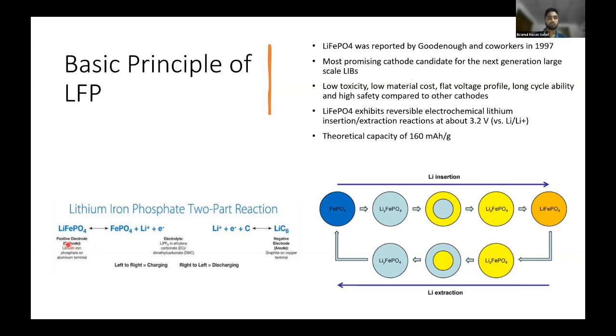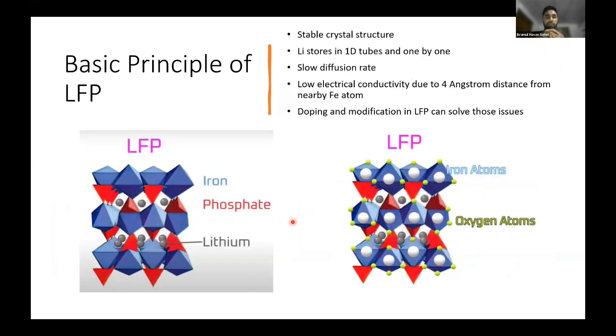So as you can see here in the reaction, when the lithium iron phosphate is fully lithiated, you get the lithium from it during the charging. And this lithium is alloyed on the anode side with the carbon. As you can see, LiC6, that means 6 carbon atoms hold one lithium inside. And that's how it goes back and forth when charging and discharging repeatedly. This is how it works for all types of battery: lithiation, delithiation, charging, discharging. And then the internal structure of the LFP, that means where lithium actually resides in an LFP. As you can see here, the structure is called olivine structure.